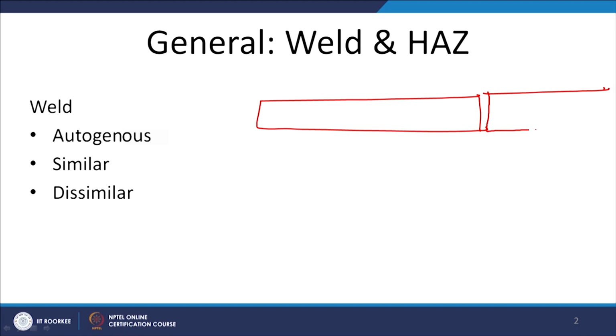Now, we will see that sometimes autogenous welding is not possible due to the difficulties associated with the through thickness penetration. Like by using laser welding and electron beam welding, maybe we can weld the thicker sheets and realize the through thickness penetration to ensure that the faying surfaces are brought to the molten state. But still in those cases, even without change in composition, a lot of structural modification in the weld metal results in the change in mechanical properties, which may be in the form of hardening or softening of the weld metal.